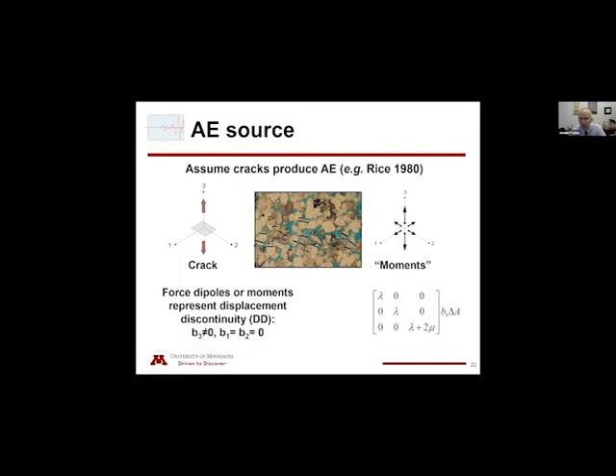Because force dipoles have units of force times distance. In seismology, this combination is referred to as a moment. So the moment tensor for a crack that's opening in the 3 direction with the normal in that same direction has this type of characteristic where lambda and mu are the Lamé constants. B is the opening of that crack, and delta A is the new surface that's created.